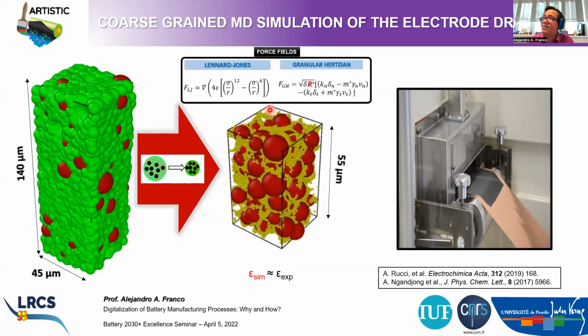So we run once again molecular dynamics. So we solve Newton equations. And then the final state of this simulation will be the dry electrode microstructure. And in this dry electrode microstructure, you see here in red the active material particles, and in yellow the carbon binder domain, which in this case doesn't contain the solvent anymore, right? And this virtual electrode microstructure can be validated with different types of descriptors, such as the porosity of the virtual electrode. And this porosity can be compared with the experimental one, right? But you can also imagine calculating the electronic conductivity of this virtual electrode, the tortuosity factor, and so on and so forth, and comparing also with the experimental values.